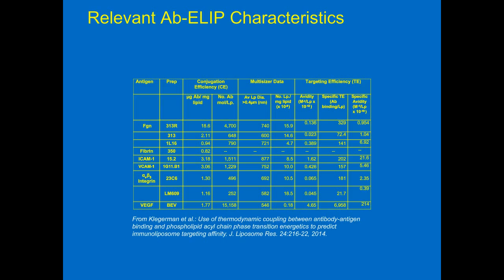Liposomes, of course, are very large. They're certainly more than 1 million as far as equivalent molecular weight. And then it's very easy to separate free antibody from the liposomes that way. The problem with that is that you get a large dilution, so you end up with a relatively dilute suspension of liposomes. There are ways of concentrating liposomes depending upon your application. We can't do that because ours are echogenic, and there's a whole lot of things that will destroy the echogenicity, any kind of centrifugation, any change in pressure, and so on.